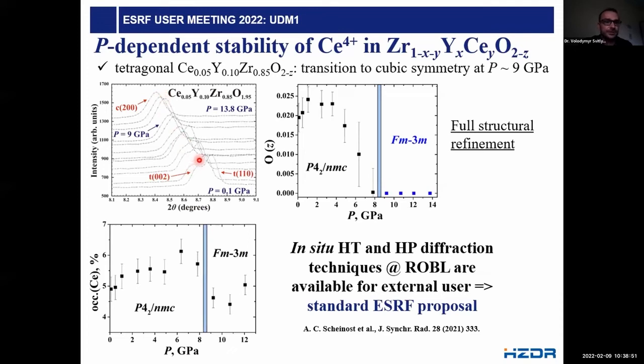You see here these tetragonal doublets merge, and you have the formation of one single cubic peak. So when you have this tetragonal to cubic transition and you remove this freedom of the Z oxygen coordinate, it should go to 0. And the point by point refinement indeed shows that this Z of oxygen decreases and then falls to 0. So this is a transition of the second order, of a displacive type.